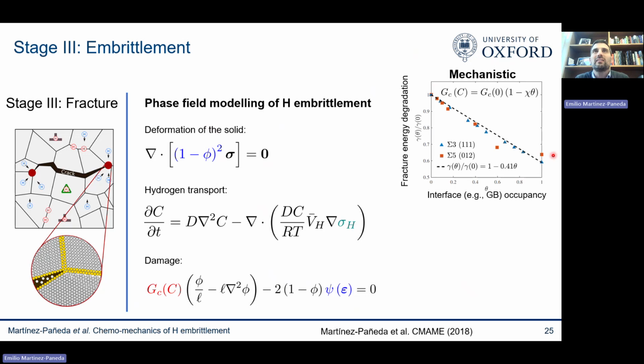One is what I call the mechanistic approach, where we basically try to understand how this happens. So we look at the atomistics, we look at the DFT, and we are able to predict how, as a function of hydrogen occupancy on a relevant interface, like a grain boundary, we can atomistically, from first principles, predict what is the degradation in fracture energy.